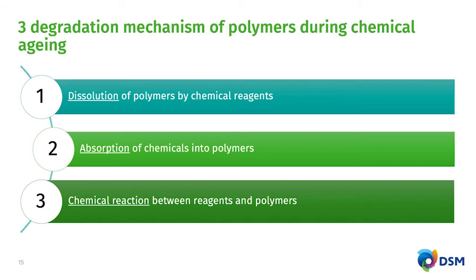The first is related to the fact that the chemical reagents used to age the polymer will start to dissolve the polymer. The second one is related to absorption of the chemicals into the polymer. And the third one is related to chemical reaction. So the polymers start to react with the reagents, and usually it leads to the degradation of the polymer itself and reduction in the properties.